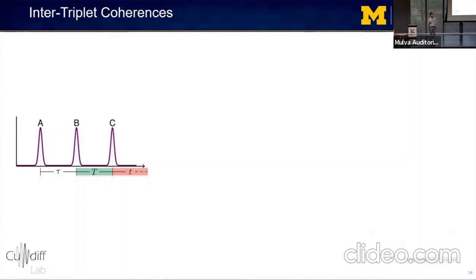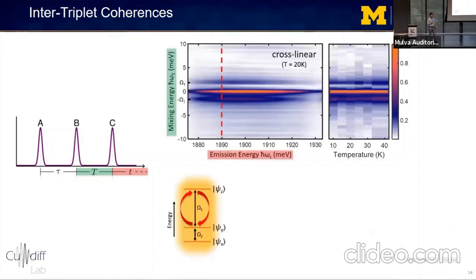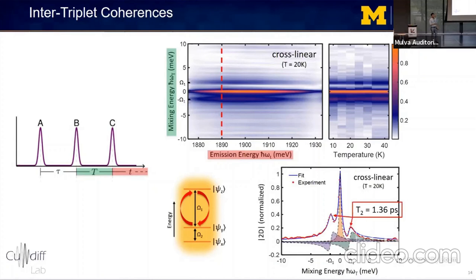We did, however, see many signatures of vibrational coherences, so I have some data on that in the extra slides if there's interest. This is what the zero quantum spectra look like for cross-linear excitation, where we see two clear sidebands that correspond to coherences between states Y and Z. And if we take slices along this red dashed line as a function of temperature, which is plotted in the top right, we see that these intertriplet coherences are quite robust against thermal dephasing, since the line width doesn't change as we increase the temperature up to 40 Kelvin. And if we fit a slice, say, at 20 Kelvin, we can extract an intertriplet coherence time of 1.36 picoseconds.